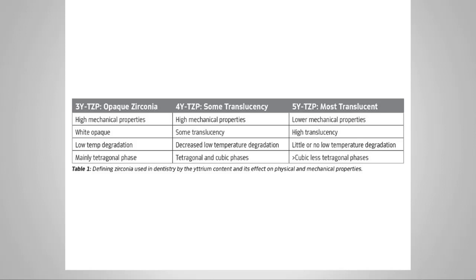If you move over to the 5 molar percent yttrium stabilized zirconia, you'll see that it does have lower mechanical properties, but it does have high translucency. So now we're seeing more cubic phase of the zirconia.